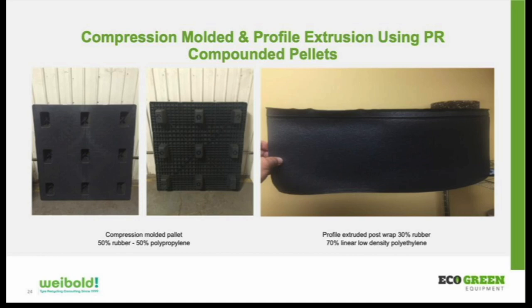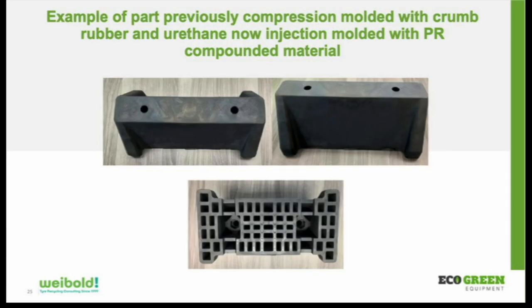The way they made this, it wasn't truly a sprue or injector. They actually produced like a football of material and put it in the press. But the point is, you'd have four points of material going into this pallet, and it works very well. The material on the right is used for wraparounds of posts or telephone poles. When they're in the ground, they'll wrap that around, and it helps to keep the wood post from getting degraded by the weather, ice, whatever, water. And that material had 70% in it. We were able to extrude 30% rubber, 70% polyethylene in that particular part. Kind of finishing up here, an example of a part that was previously a compression molded piece.